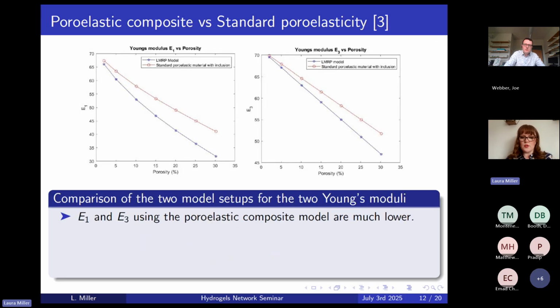And okay, so now to present some of the results that are coming from this. So here is a comparison between the two model cases for the Young's modulus E1 and E3. So E1 is the modulus when we are pulling on the side of the cube where the cylinders are running vertically in this direction like this, and we're pulling this way. And the E3 is pulling in the direction that the fibres and channels are elongating. So that's what we're comparing here. And we can see that using our new model, which is this blue line, we get lower results for both of them than the standard poroelastic approach.